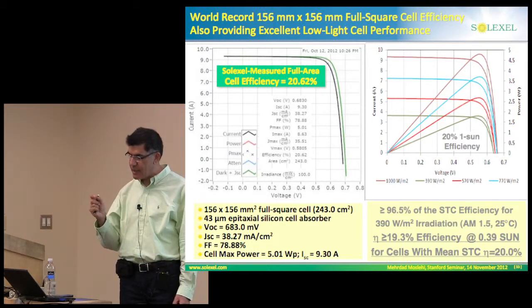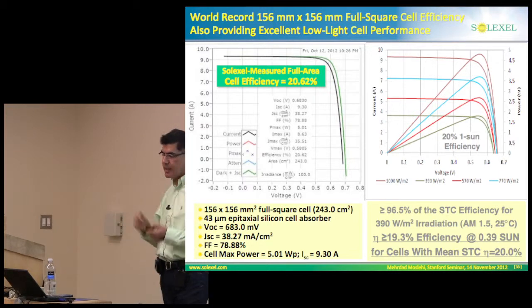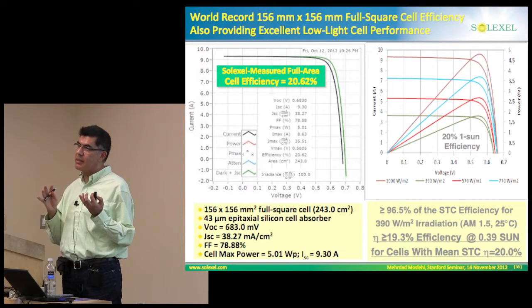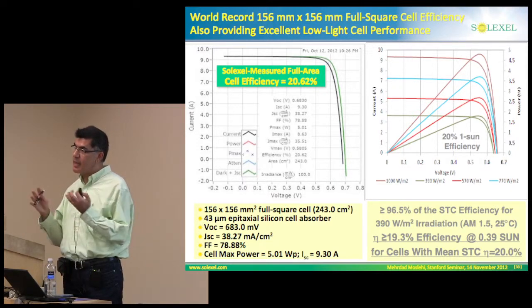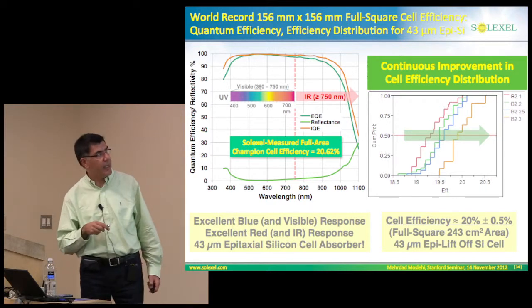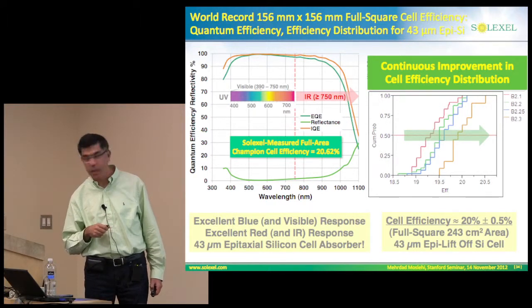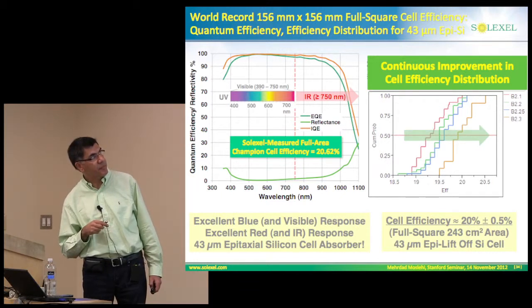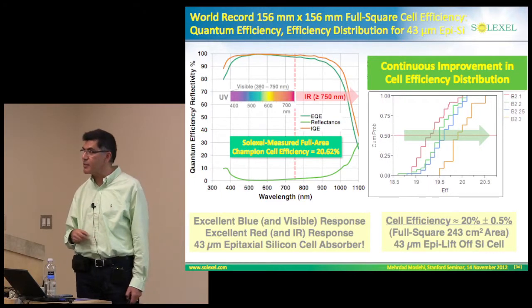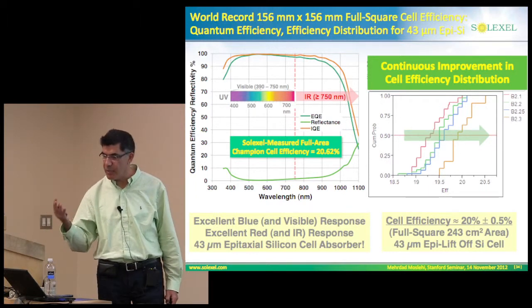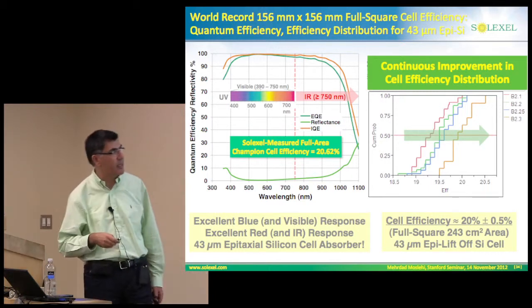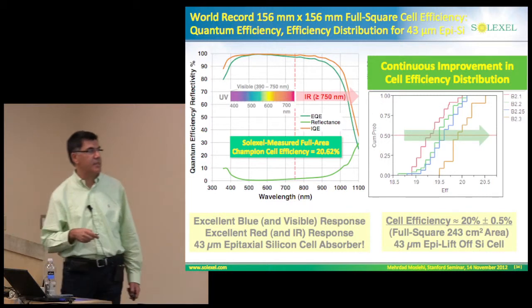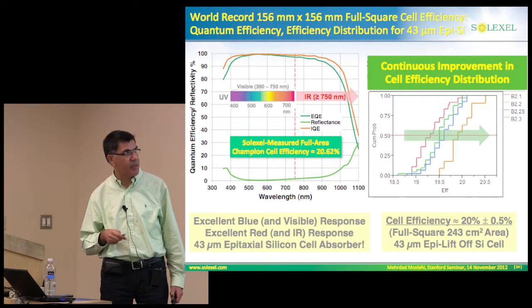Because of excellent bulk lifetime, which is greater than 300 microseconds in our technology, surface passivation below 10 centimeters per second, and also light trapping structure, we actually achieve pretty decent quantum efficiency. What you see here are the internal and external quantum efficiency. This is IQE, this is EQE. The difference is accounted for primarily by the reflectance or optical reflection losses in our cells. Our weighted optical reflection loss is around 2.5 to 3%. So this represents a very good performance in our thin silicon cell in terms of quantum efficiency.